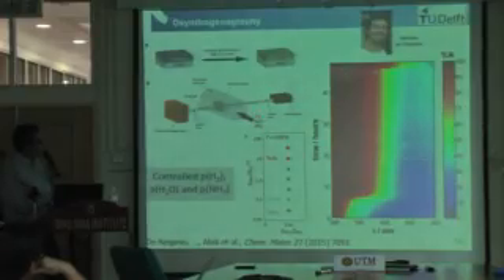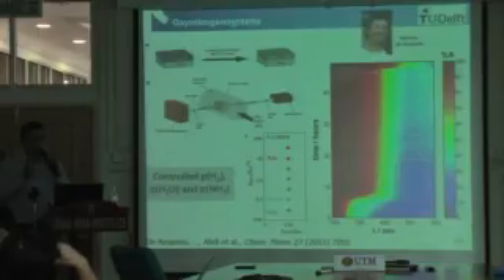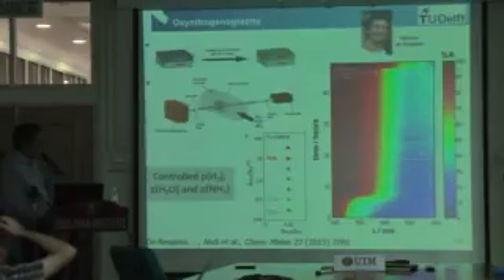So now we added, so Moreno is my PhD colleague from Delft when I was there, we introduced additional control to the experiment. Instead of only flowing ammonia, we also flow hydrogen and water. What it does is that by controlling the partial pressure of hydrogen and water, we control the partial pressure of oxygen, right? So in a way, we're controlling the partial pressure of oxygen and nitrogen at the same time and trying to titrate oxygen and nitrogen into our lattice and out of our lattice. Once we controlled all of this, we did it as a function of time, but also as a function of different partial pressure ratios. To sum up, we were then able to get this elusive beta tantalum oxynitride phase by using this oxynitrogenography.